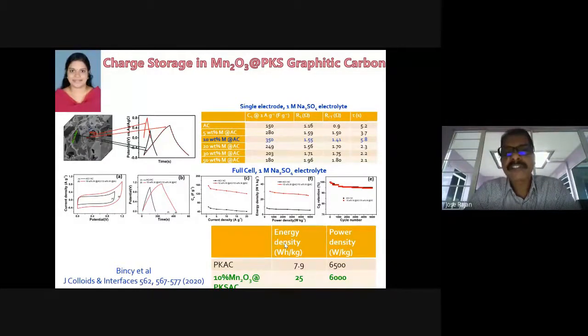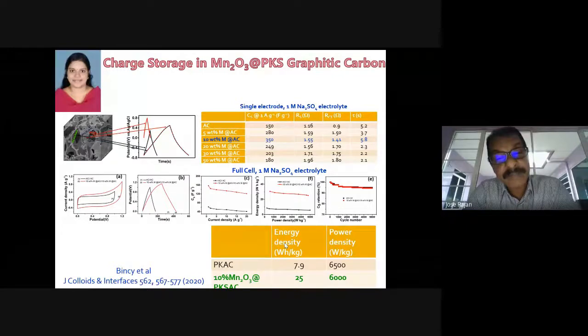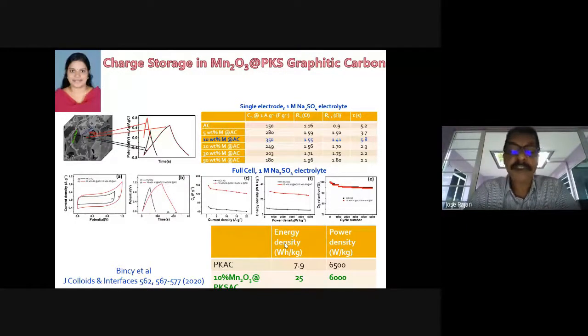When we have this metal oxide coated palm kernel shell carbon, you would see that the energy density increased more than 3 times. And what happens to the power density? Initially it was 6,500 watt per kilogram, which means it can be charged quickly. And when you look at the power density of the metal oxide coated carbon, it did not decrease much. Usually, when the energy density is increased, the power density decreases drastically. In this case, no such drastic decrease in power density is found. So that's a good strategy.